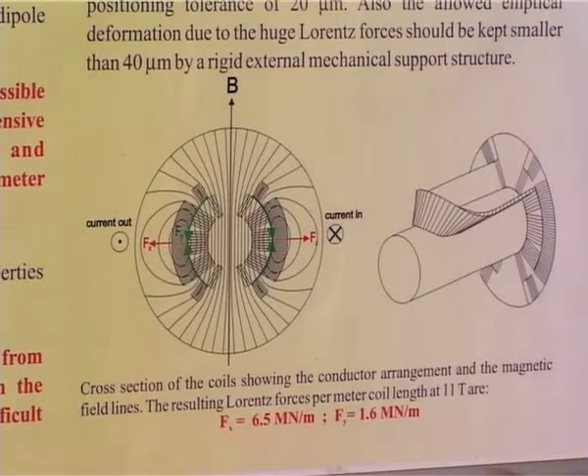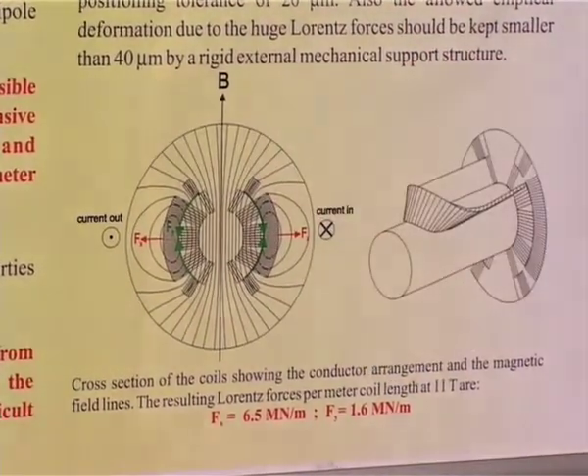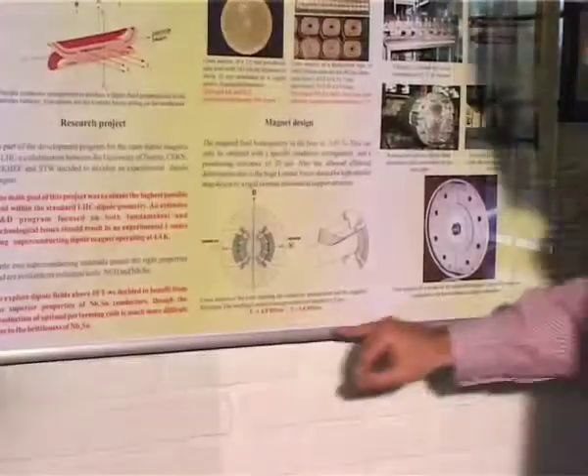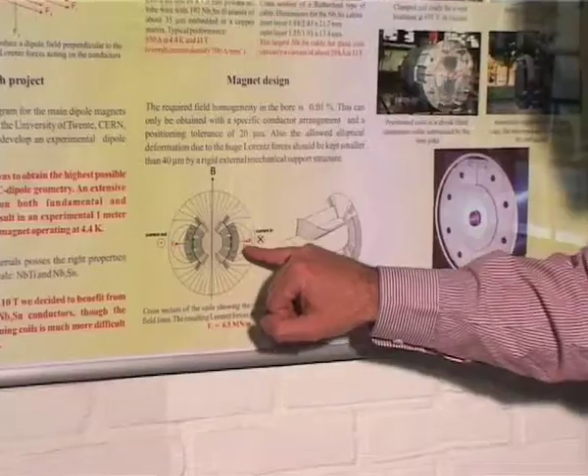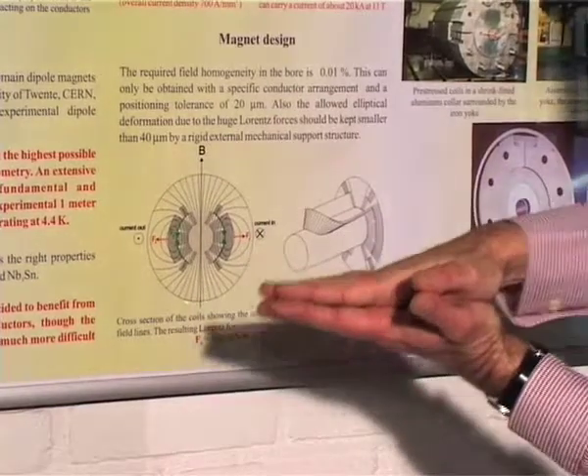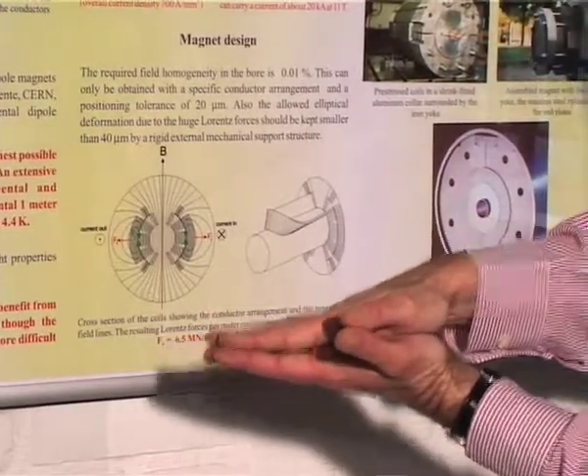At the same time, the two halves are pushed together here with a force of 1.6 MN per meter. And for niobium-tin coils, this is the most dangerous one, the green one. So it's a force pressing on the cables, pressing on the individual strands in the cable. It's also very difficult, by the way, to make good, highly compacted tin cables because you destroy these beautiful strands during cabling because cabling is a horrible process, compacting the things in these flat Rutherford cables.